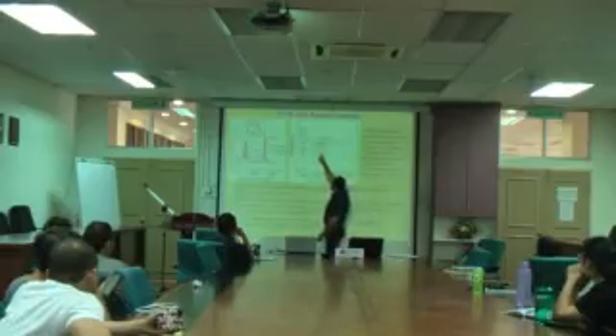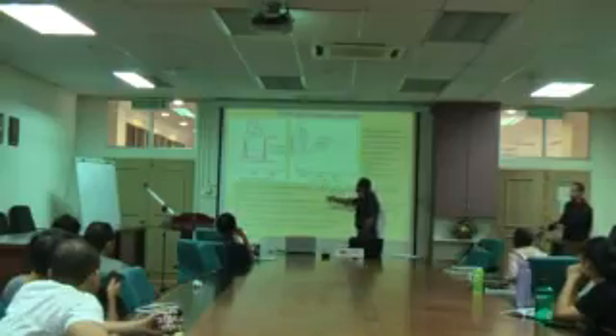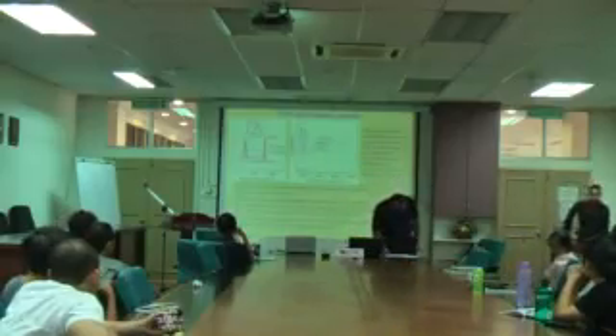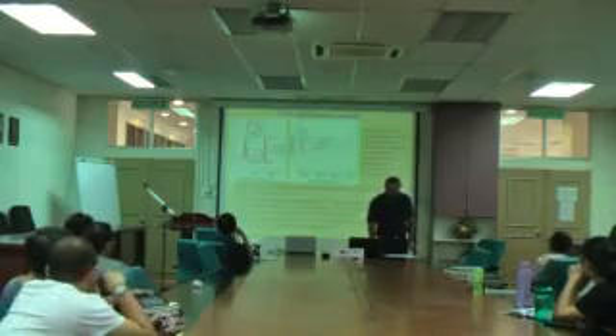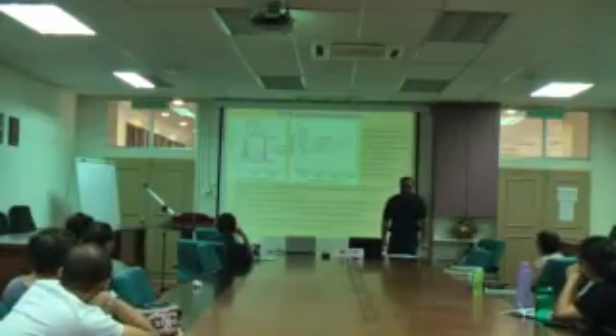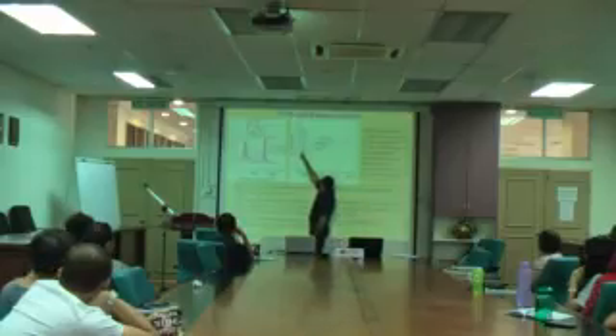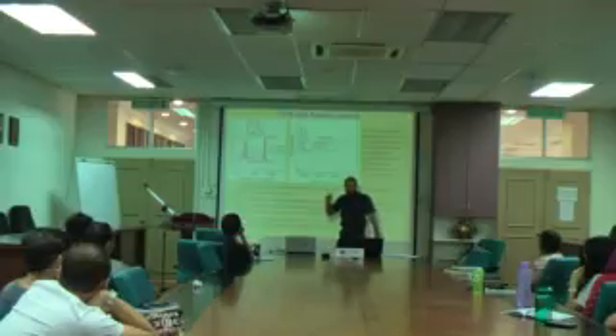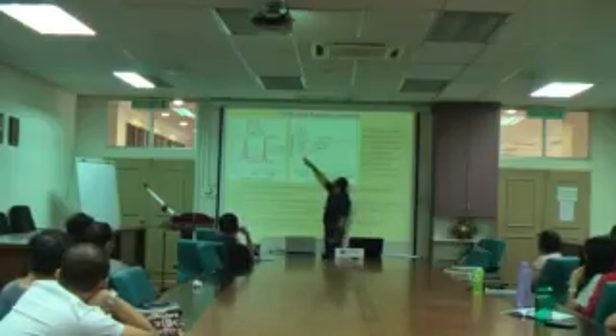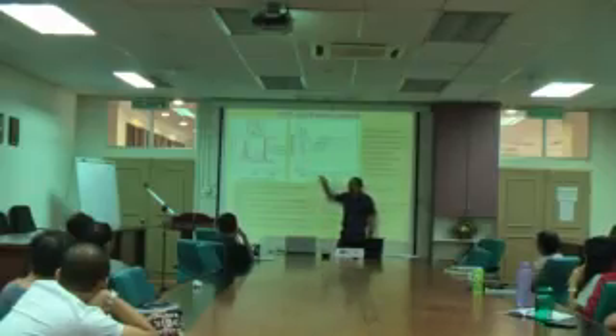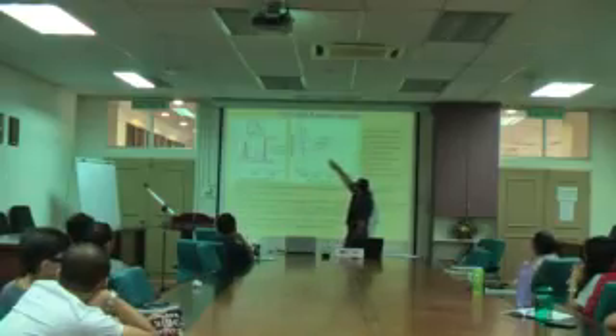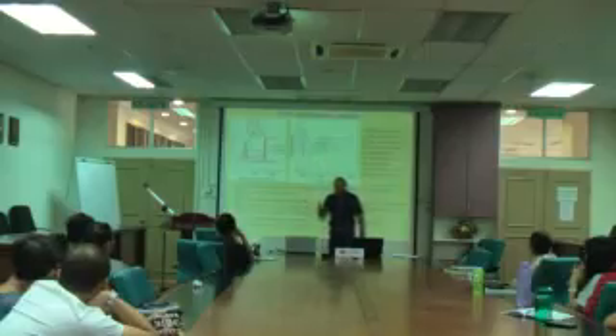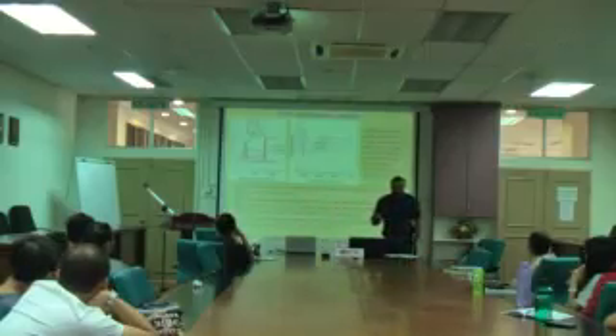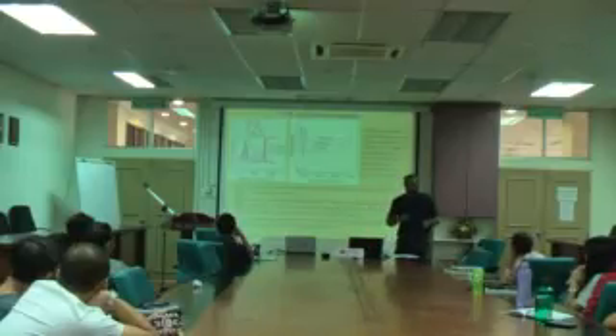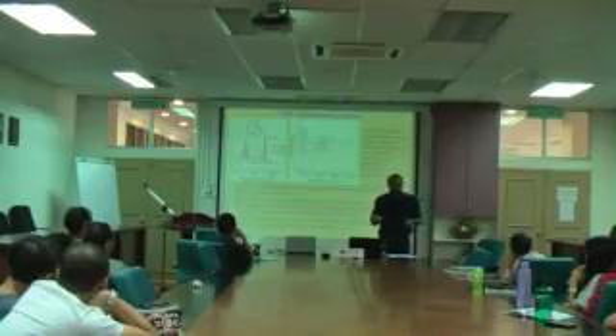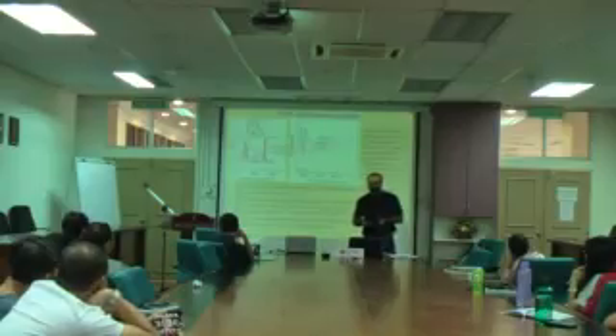I just know that by increasing the annealing temperature, this peak is related to symmetric stretching and asymmetric stretching absorption modes. So symmetric for SiO and asymmetric stretching absorption mode for germanium oxide. By increasing the annealing, first we can see the interdiffusion of oxygen in the germanium causes this to increase. By further increasing to 700, this peak shrinks, I guess because of, maybe, the exhaustion of the germanium suboxide. I don't know. This is my idea.